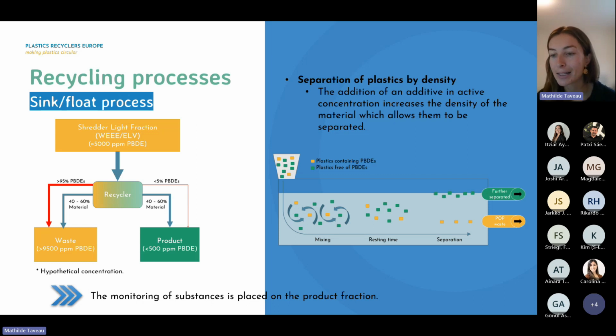This is the process explained in a little more detail, really the sink float. What is happening here is that you have, let's say, some plastic particles. I would say at the beginning, they're roughly between 2 and 3 centimeters of diameter, or rather a square maybe. And they're placed in the hopper, then they're entering the sink float bath, then there is a mixing process to ensure that all the flakes are placed homogeneously in the bath, and then you have the separation process through the resting time, and then you have the 2 fractions that are exiting the bath.